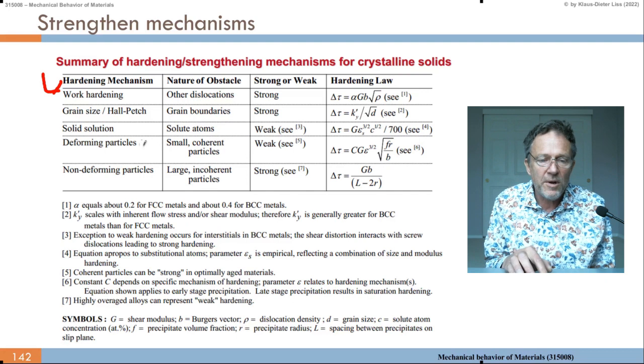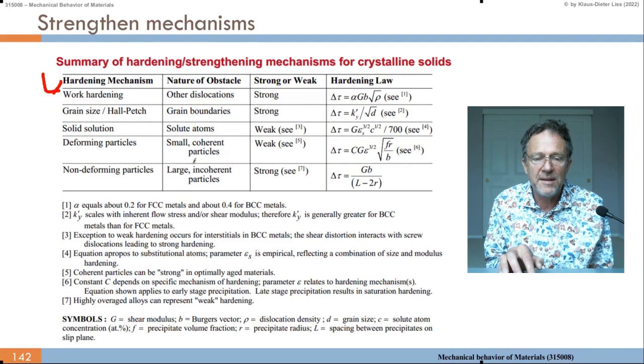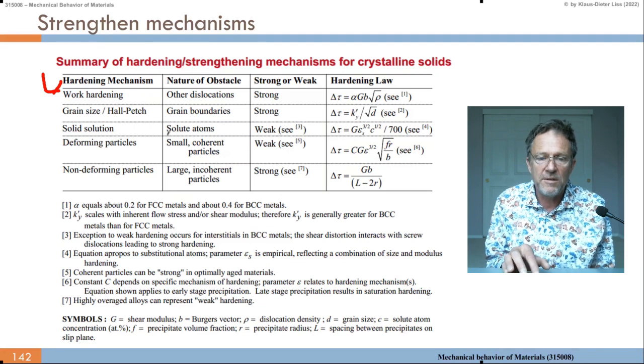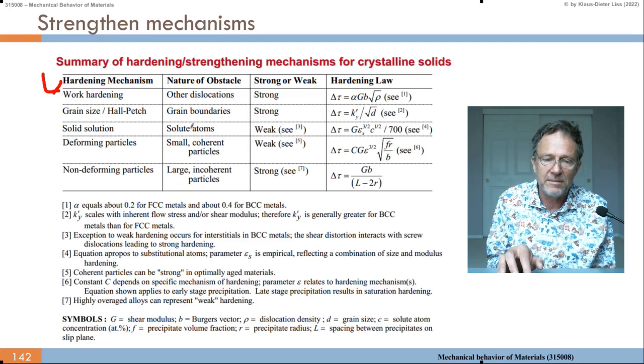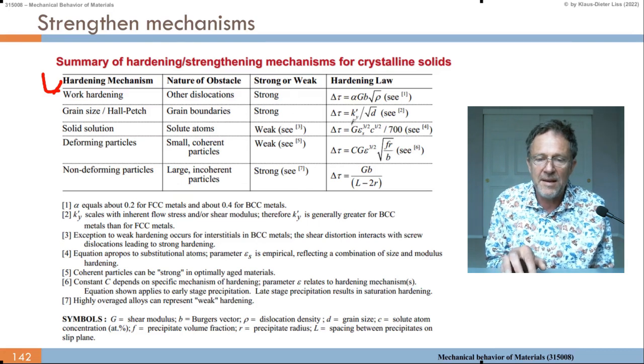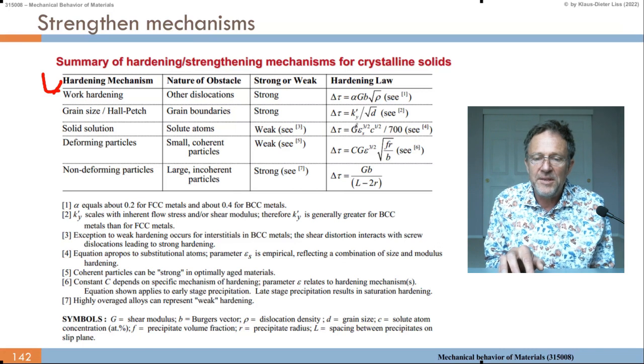I'm sorry, I jumped already here to the deforming particles. So deforming particles is where we have small coherent particles, such as Guinier-Preston zones and theta precipitates of copper in aluminium. They are also relatively weak, so that goes with the precipitate volume fraction times the precipitate radius divided by the Burgers vector, square root of it. Back to the solid solution, sorry, I messed that up. Delta tau becomes G, epsilon to the 3/2, c to the 1/2, divided by 700.